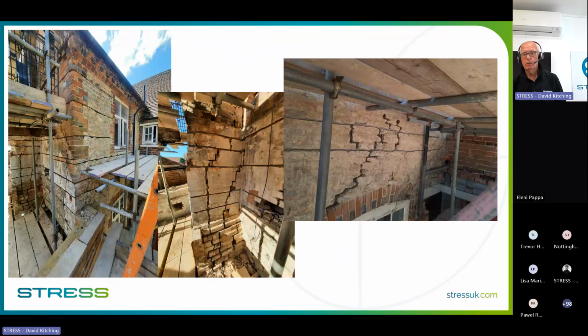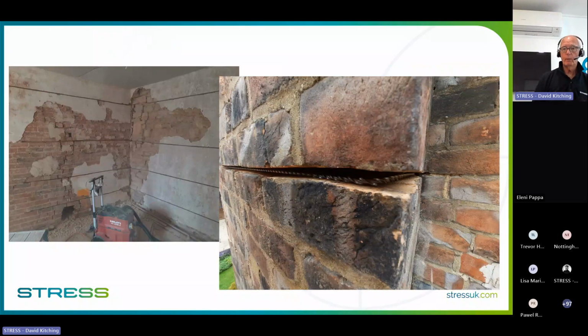So when it comes down to the installation, you can see here that we've got stonework, and it's fairly regular stonework, but the blocks themselves aren't exactly square like brickwork. They've got slight curves to them, and the blocks are slightly different sizes. So the bed joint isn't straight. If we ran our chaser straight into that bed joint in a straight line, when you do the repointing, those two lines that you see there would be straight and all the other pointing would work around the blocks. So you can't do that. You have to hand chase those in, a little bit more work around the blocks, and you will get a slightly uneven line. When the helibar's put in, as it is there, repointed, you won't see it. It will completely disappear. If, however, you are going into brickwork, you want to follow the bed joint, and the bed joint normally will be straight.